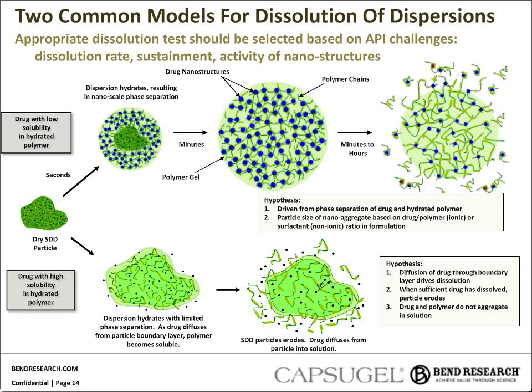The bottom part of the model is different. We usually see this with an ionized drug form or something that has a fairly water-soluble side to it, maybe an amphiphilic molecule. Usually these drugs have high solubility in the hydrated polymer, and therefore it acts more like a standard matrix tablet, where you'll get a lot of erosion and free and micelle drug leaving and being formed, and this particle only erodes at the rate at which saturation in the dissolution environment takes place. So we get diffusion of drug through this boundary layer driving dissolution, and when the drug is dissolving, you now have a hydrophilic polymer and this particle continues to erode.